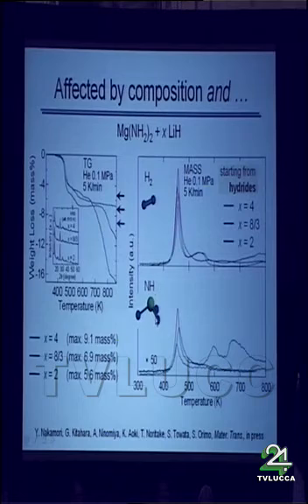So here's our actual result on the hydrogen and ammonia emissions. Here's a result of TG, and also here's a result of mass spectroscopy. Simply speaking, the amount of ammonia formation can be suppressed by increasing the amount of X, that is, by increasing the amount of lithium hydride. But in this case, not only composition, but also the starting materials are important.